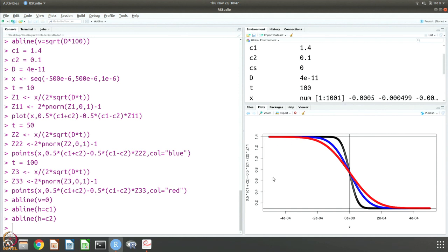Of course, after an infinite amount of time, you expect that everything becomes 0.75. That is the composition that the system is trying to reach after an infinitely long time. But as the time proceeds, you will see, for example, how much diffusion took place in 10 seconds, and from 50 to 100 it is less, because the concentration gradients are coming down as diffusion progresses. This means it will take longer and longer to achieve the same amount of diffusion. So things also get slowed down compared to the initial stages. It will take a really long time for the composition to reach the uniform value everywhere.